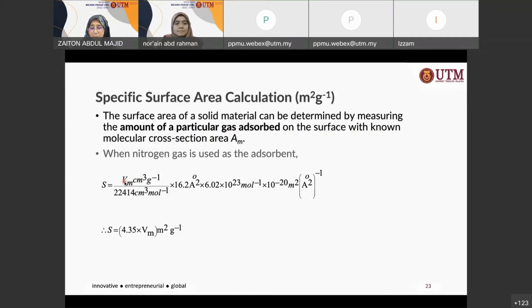So in this case, the Vm is obtained from your BET transformation plot, multiplied by the cross-sectional area of your liquid nitrogen. This is from nitrogen if you're using nitrogen as the adsorbate gas. This is your Avogadro constant, and divided by the volume at STP. So this is the generalized surface area calculation if you're using nitrogen as adsorbate gas. If you're not using nitrogen, then this value will change. So the value 4.35 will also change, right? Most often in our samples, we use nitrogen as the inert gas, as adsorbate gas. So most often the student will use this formula here for the calculation of the specific surface area in meters squared per gram.